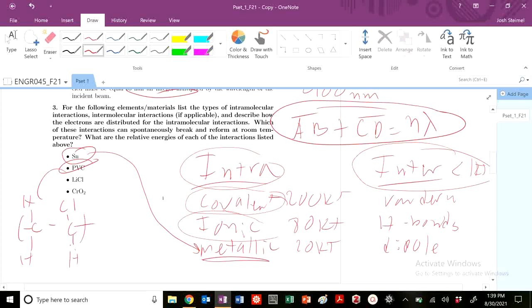So, what interactions are going to occur here? Well, we've got covalent bonds along the backbone, but then we'll have these van der Waals interactions with the chlorine. You might have some dipole-dipole interactions because it's very electronegative. And just by changing this chlorine to an H, we get polyethylene. But PVC is essentially much stiffer than polyethylene, and it has a much higher Tg than polyethylene, just due to that chlorine group. So very interesting, to me at least.